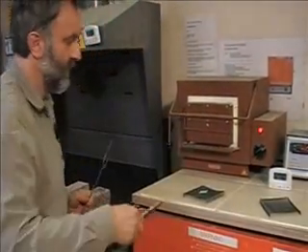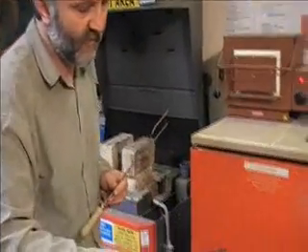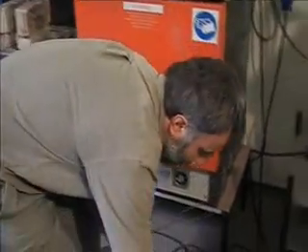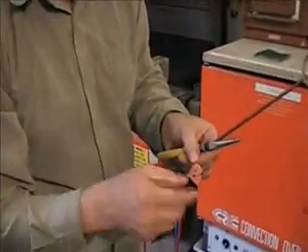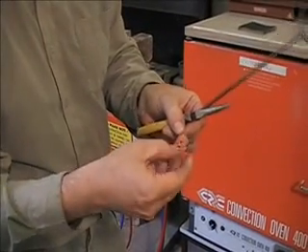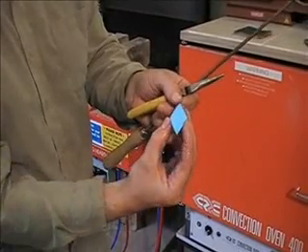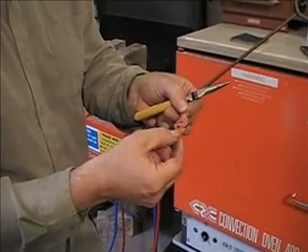The easiest thing to do is to pick up the mesh with a pair of pliers. We don't want to tip the whole mesh in the water, and hopefully it won't be stuck and it will just tip off like that. It's a bit of a messy job putting out. Leave it a couple of seconds to cool down, and as it tips into the water you'll see that most of the flux that has formed on the back, most of the scale that's formed there has come off, and we might need to take off a little bit of that, but that won't take very long. So we should end up with a slightly wet thing but with a nice blue surface there and a fairly clean copper back, which is then ready with a little bit of preparation to put some